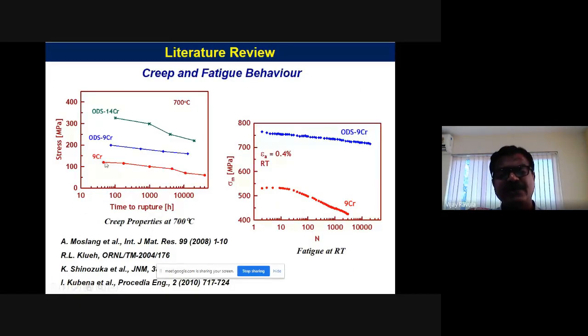So typically, if you see the stress levels for different time levels, between the 9 chrome and the ODS 9 chrome, you can see that there is a lot of jump. And similarly for the fatigue life also, 9 chrome to the ODS, the stress goes up like anything, and it can take more number of cycles also. So that's an advantage. So on that we have embarked on a major program on developing these materials.